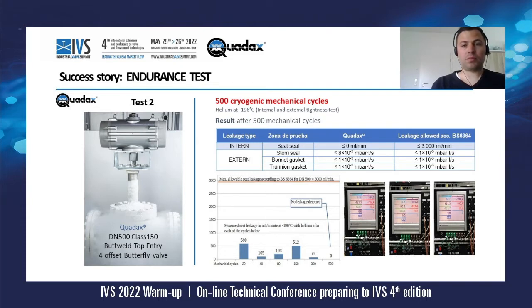The same thing here in the endurance test. You can see here on this slide the leakage rates, and you can see here on top the maximum allowable seat leakage rate according to BS 6364 for a DN500 valve. And you can see that the Quadax valves on the mechanical switches test were far below the limits, and at the end, zero leakage was detected at all, which was the best result that was ever achieved from a cryogenic butterfly valve.